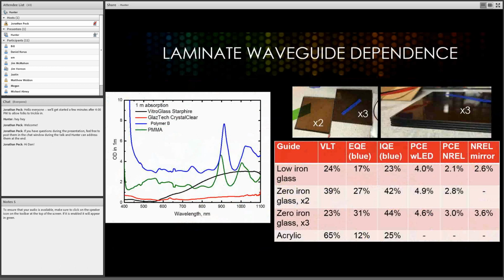Another key one is the quality of the glass. There is a trend in the industry moving away from typical float glass, which has this green color. If you take a sheet of that and look on the end of it, it'll look almost black. That's because of the iron added to that glass as part of the manufacturing process. It forms iron oxide essentially, and that will absorb light, which you wouldn't notice through an 1/8 inch or a 1/4 inch. But when you look the other direction, it makes a big difference. And we actually have to couple light through the long direction. So that glass doesn't work very well.